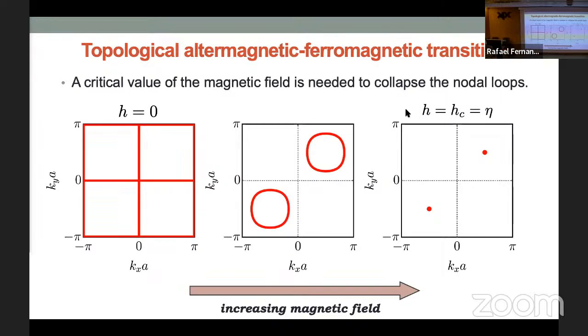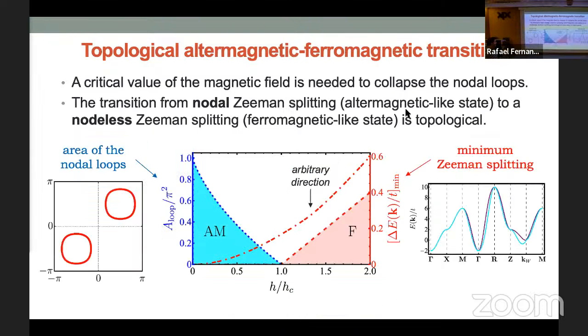This is nothing but a topological transition, where I have to eliminate or kill completely the nodal lines. So I think this is the main thing I wanted to point out: when I go from an altermagnet, which has nodal lines, to a ferromagnet in the sense that I don't have nodal lines, this transition is a topological transition if I apply the field perpendicular to one of the mirrors. In an arbitrary direction, you immediately get a ferromagnet. Okay. All right. Do I have 5 minutes just to go over the?